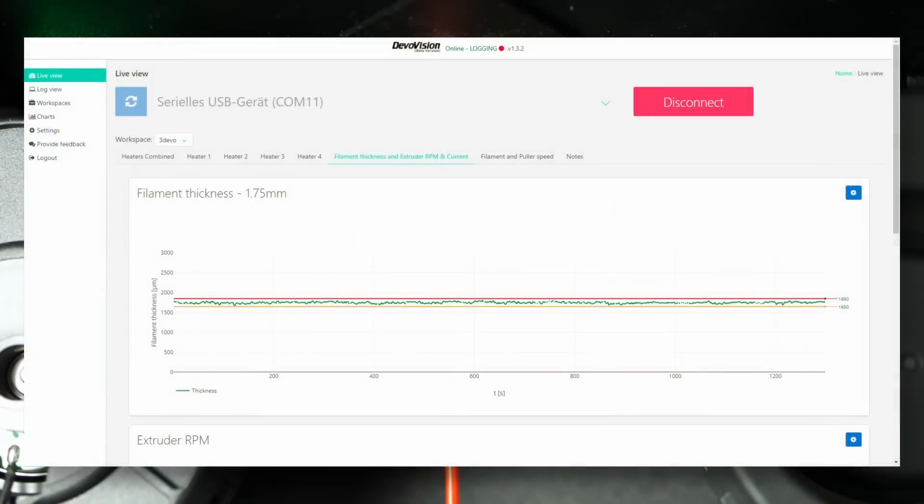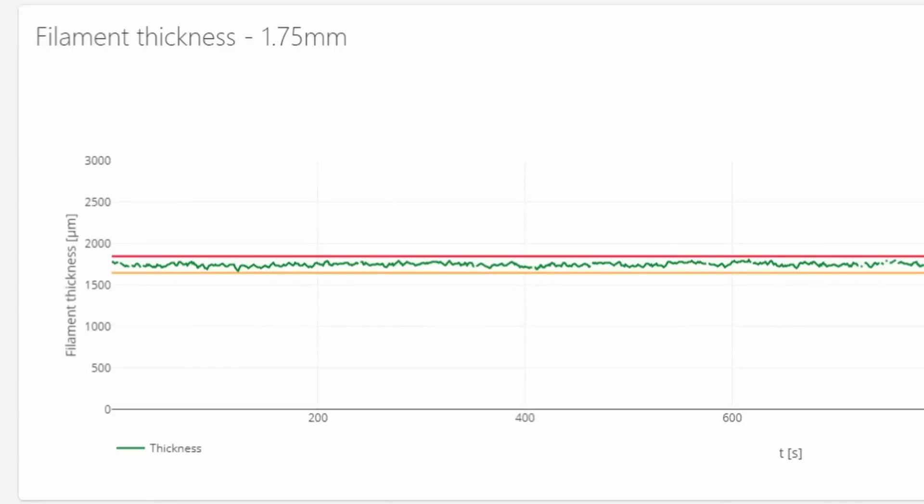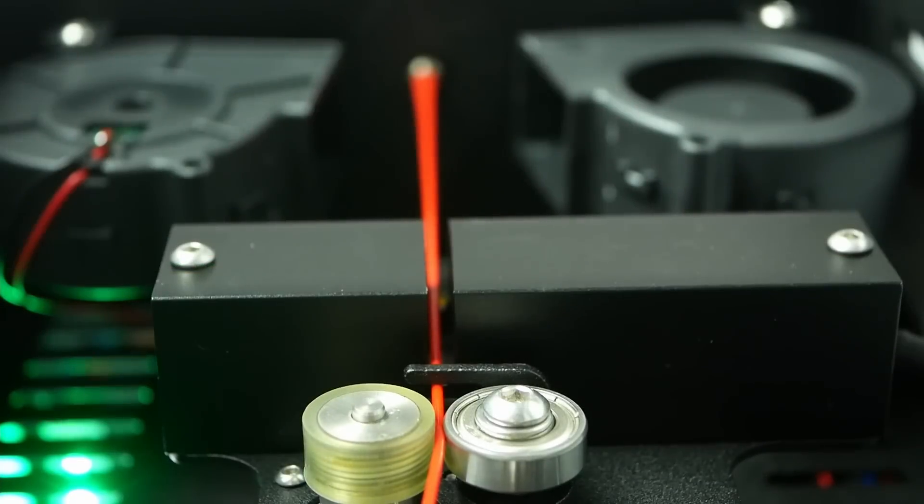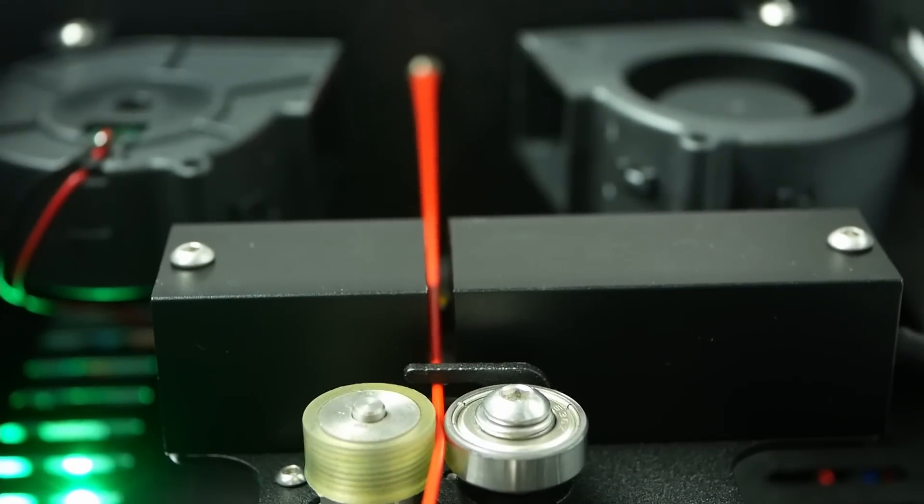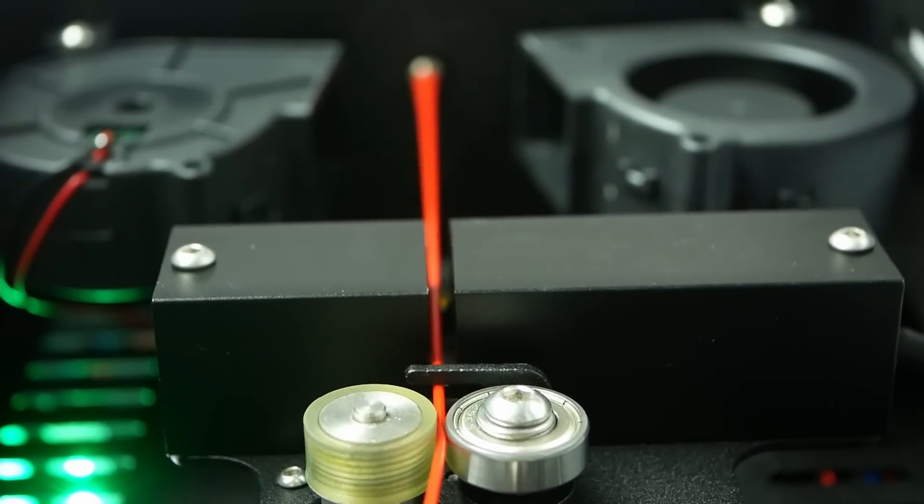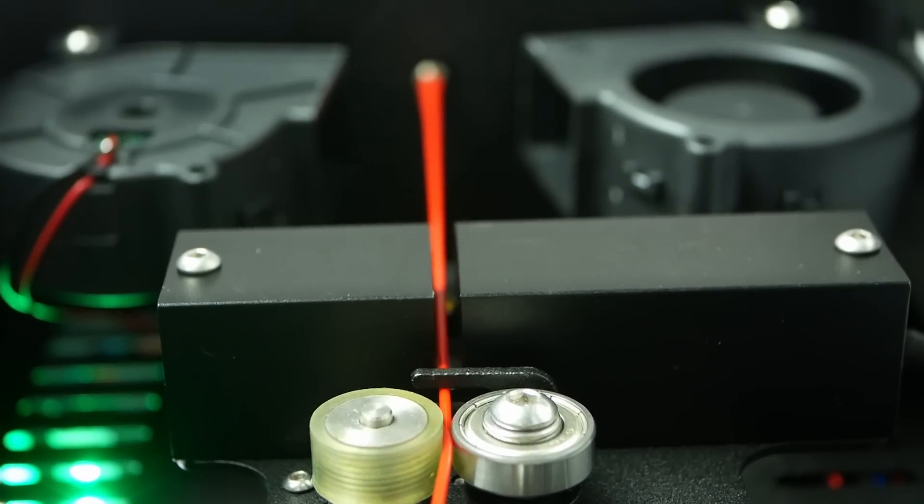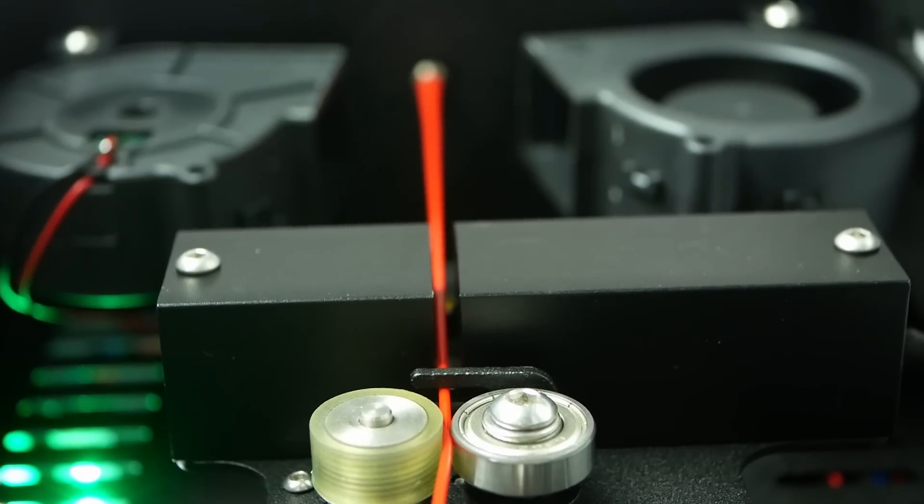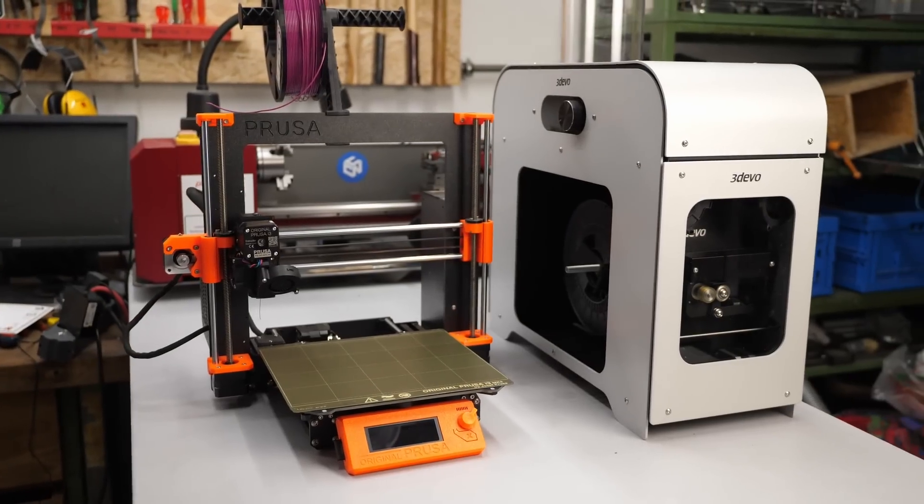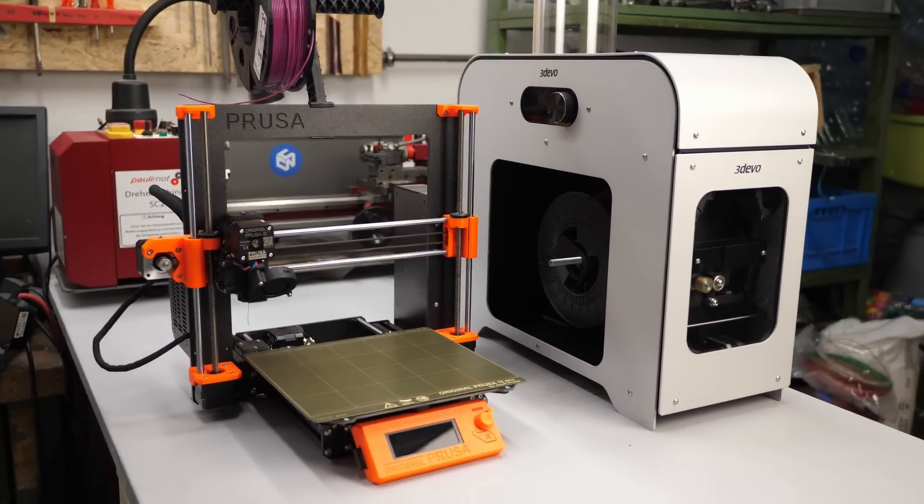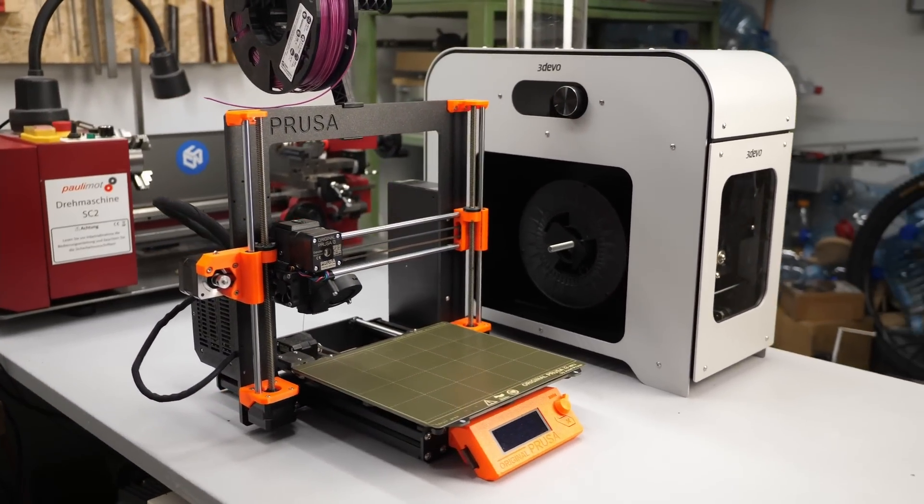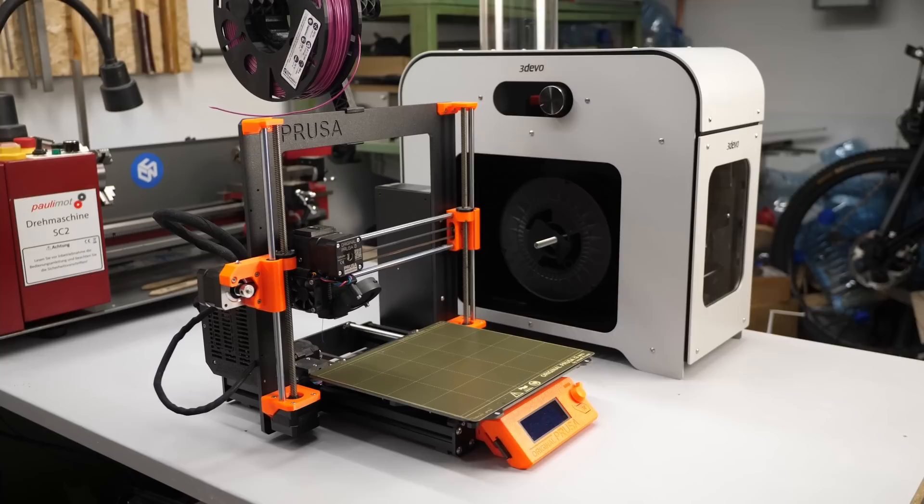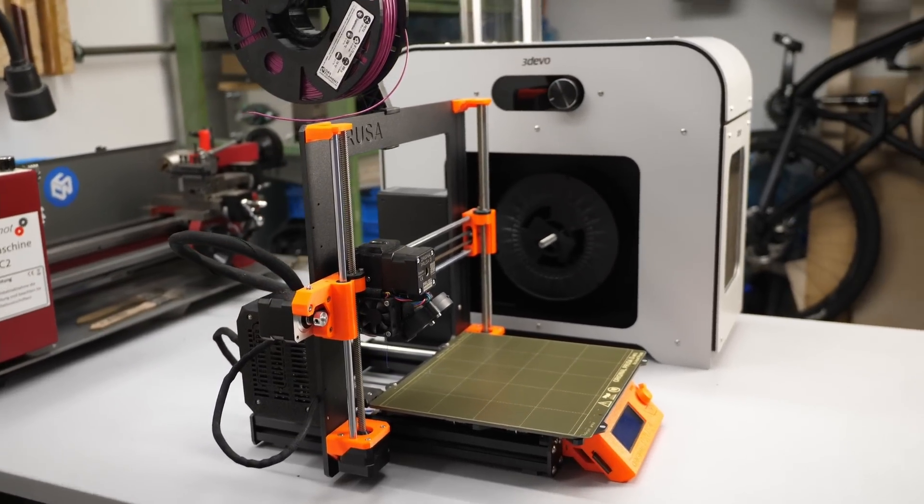3Devo provides, besides their extruder, monitoring software that you can use to track all the extrusion process parameters. In our case, when we only extrude simple PLA, the diameter is what concerns us. As we can see, the diameter fluctuates a little, mostly between plus or minus 0.05 mm, sometimes a little more. I have already tried to tweak the process parameters even more using different temperatures, fan settings and screw speeds, but since I'm just starting using this machine, I'm okay with the results. Honestly, if you look at the size of the machine that is just using as much desk space as a Prusa Mark III, you can't expect the preciseness of an industrial extrusion line.